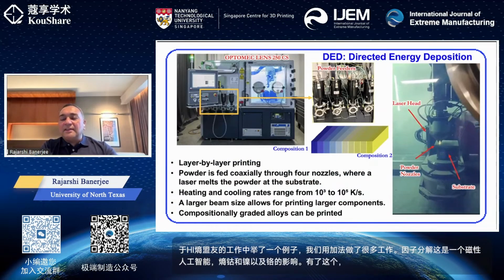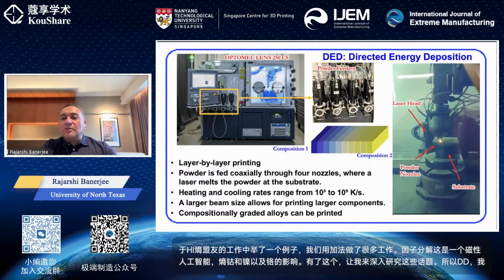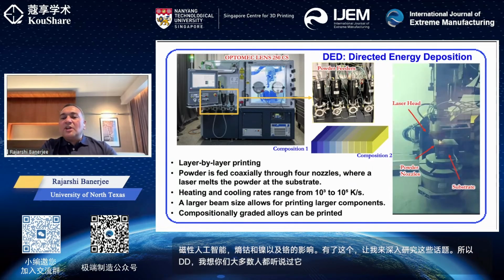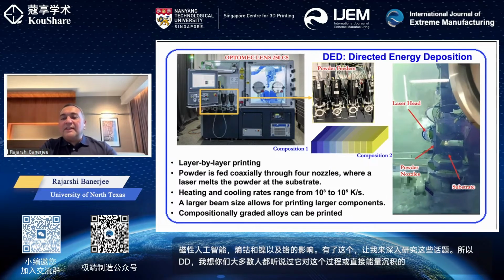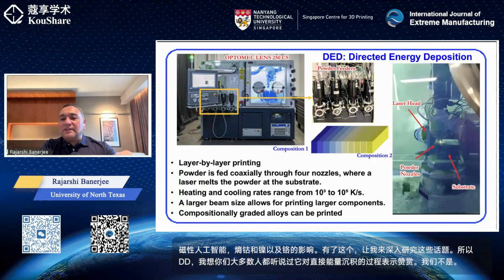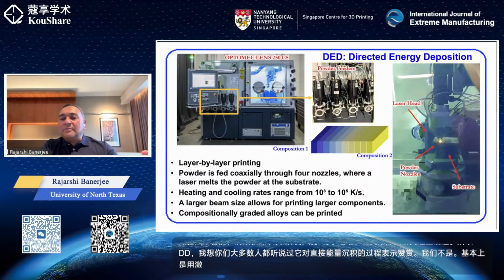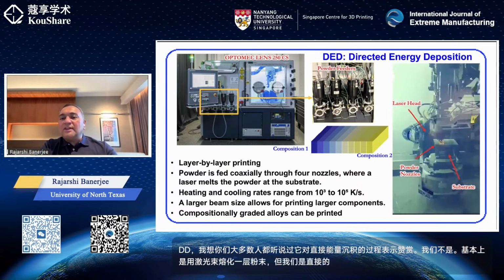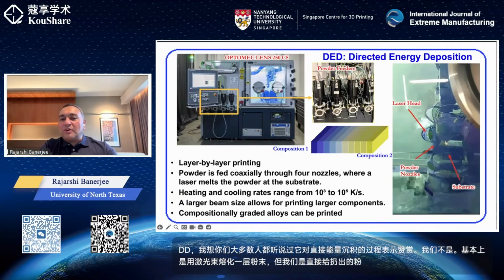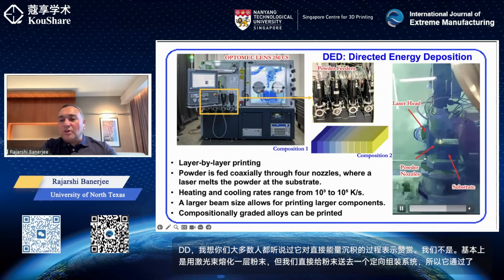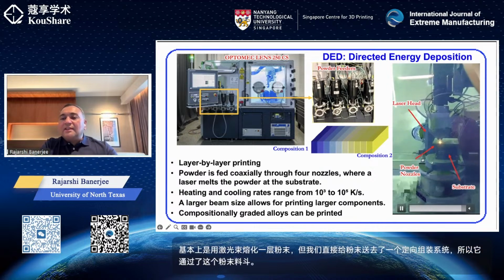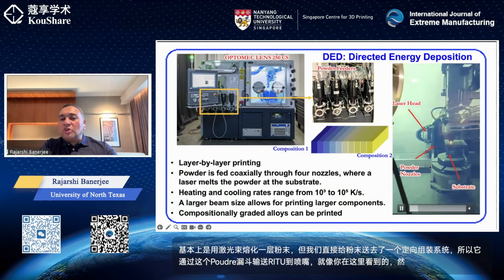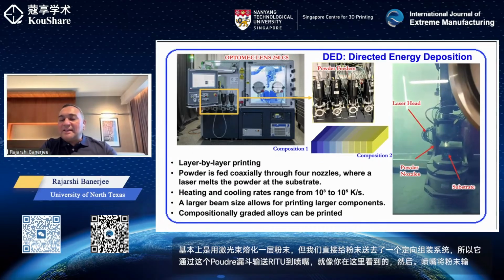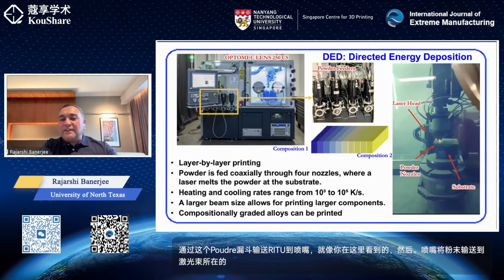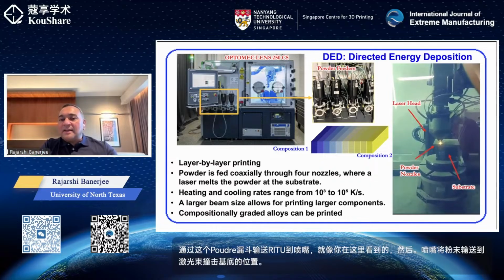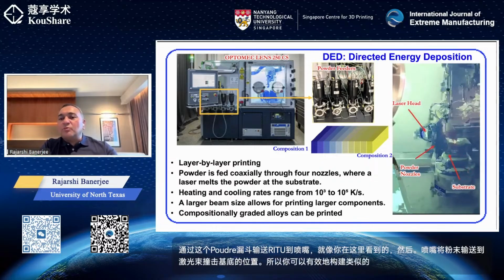So DED, I think most of you have heard of it. It's a blown powder process or directed energy deposition. We are not basically melting a bed of powders with a laser beam, but we are directly feeding the powders through a directed assembly system. So it goes through these powder hoppers. The powder hoppers deliver it through nozzles, as you can see here, and then the nozzles deliver the powders to the location where the laser beam is hitting a substrate. So you are effectively melting the powders that are kind of blown into the localized melt pool on the substrate.